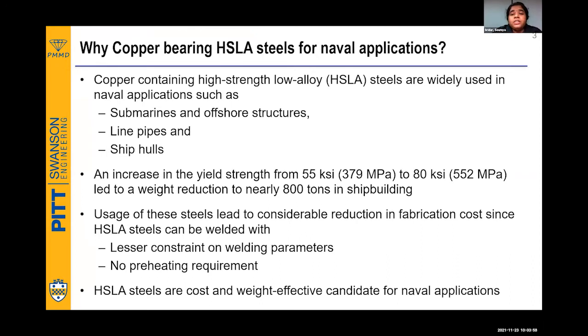So some 55 KSI to 80 KSI increase in yield strength, the weight reduction is nearly 800 tons. It's a huge number. And so it's a weight effective way of dealing with the material. And second thing is, again, we are going to have very good weldable steels. Steels with very good weldability means we are reducing the fabrication cost. And how the weldability has been improved, like having lesser constraint on the welding parameters, and most importantly, no preheating.